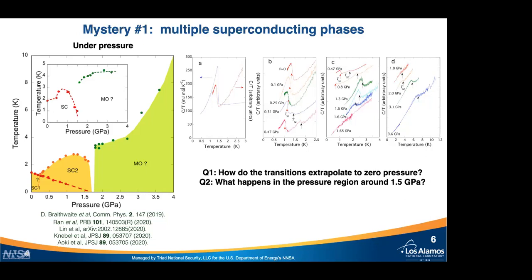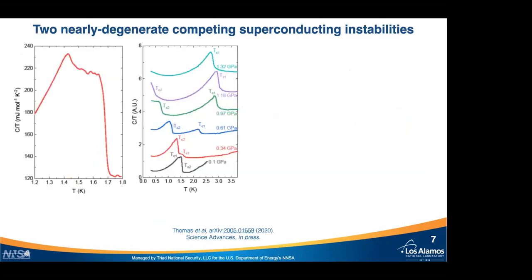It seems to be really first order like, and we wanted to explore this part of the phase diagram, especially because of the possibility of a quantum critical point. Okay, so these are results obtained in our group here in Los Alamos. The first plot on the left shows an adiabatic heat capacity measurement, not in the pressure cell, just to show that even at zero pressure, if you do a so-called heat pulse measurement really close to TC, you can see two peaks.